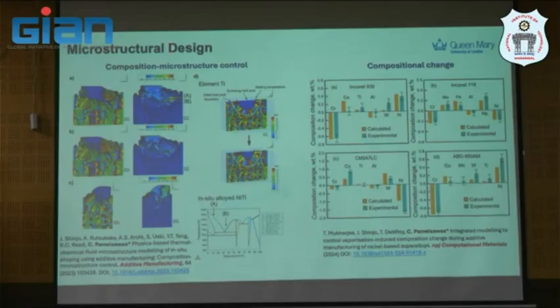Another impact on this microstructure design is composition change induced by the process, because our previous work noticed that there is some change in the composition, especially the high vapor pressure element like chromium, and even nickel itself is also prone to vaporization. So with the collaboration with Professor DebRoy and Dr. Mukherjee in the US, we can get some predictive capability of the composition change during the 3D printing of these 4 nickel-based superalloys. I think that is relevant to the context in the previous slide that I mentioned. We will try to understand more why this one is non-printable.